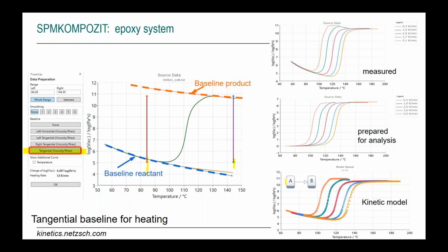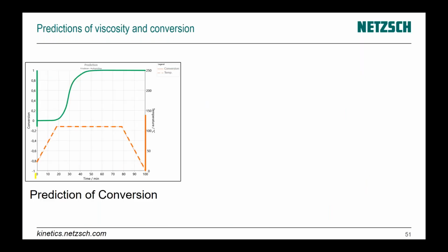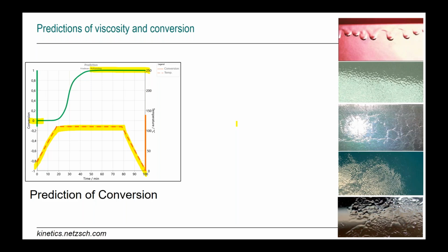Here is the kinetic model, where modeling is done. Points are experimental data, and lines are our model, which can be used for predictions. Now for predictions, we can put in any temperature profile and use this model to see how a reaction proceeds. Here is temperature, and here is degree of conversion, which is 0 at the beginning and 1 at the end, and here some curing happens.